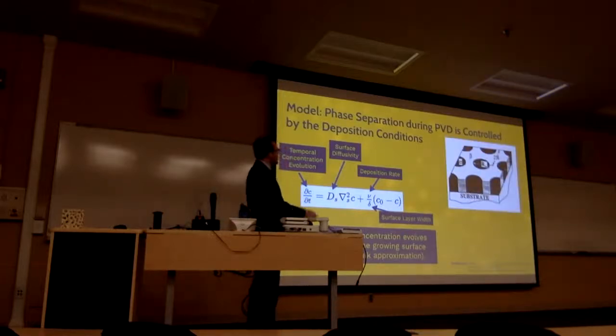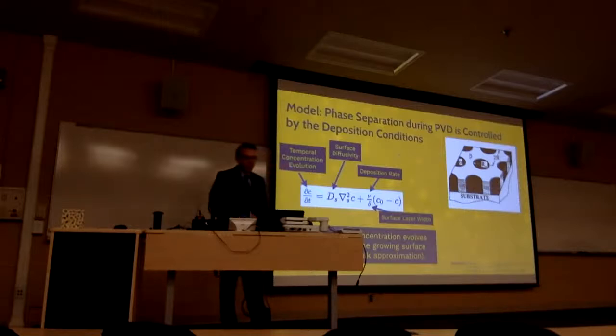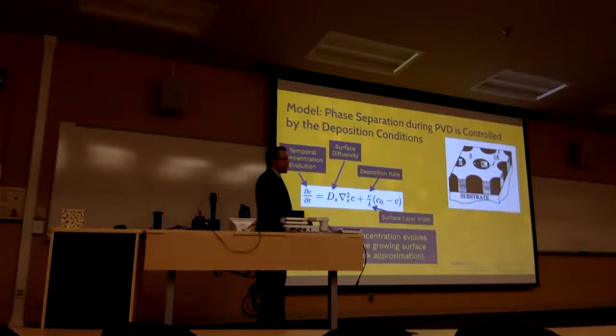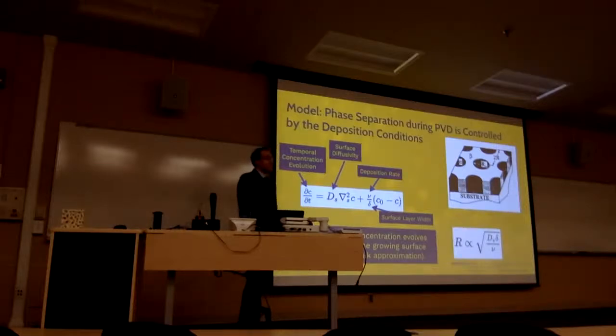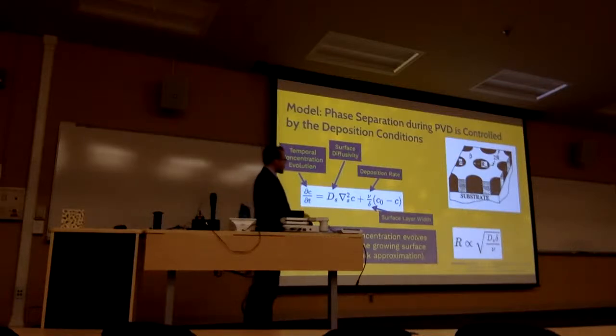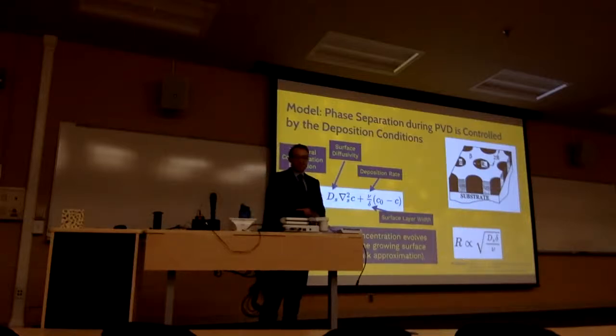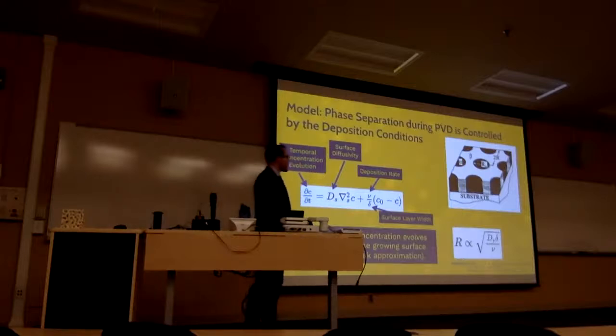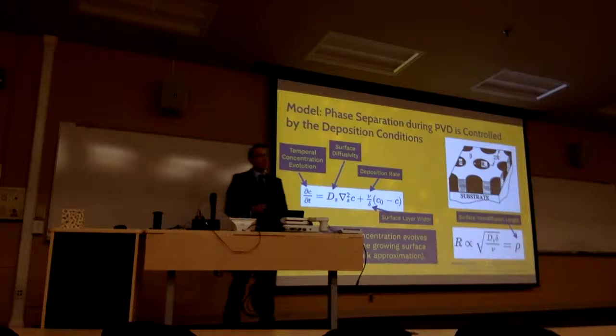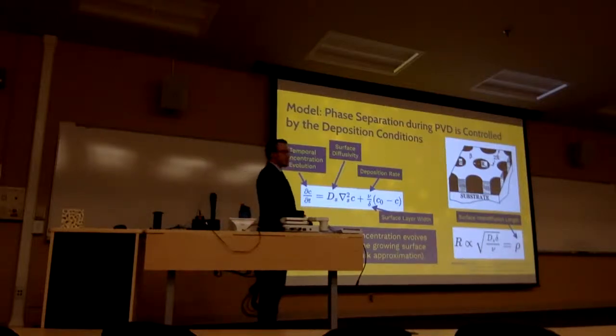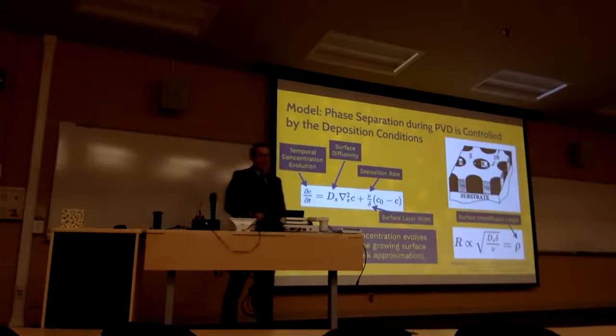So they idealize a structure that looks like this. So this is an alpha and beta rich morphology where you can see those phase separated designs at some length scale R. So that measures the domain size of that structure. And what they saw, what they concluded, is that that domain size R is a function of how far an atom can travel on the surface before it's buried by the next incoming deposited layer. And you could actually recognize that these two things are proportional. This actually, on the right-hand side, describes how far an atom can travel in diffusion, just like the Einstein relation. So they describe the surface interdiffusion length depending on the deposition conditions, namely the temperature, which feeds into this D variable, the surface diffusivity, and nu, which is the deposition rate, how fast we're adding material to the system.